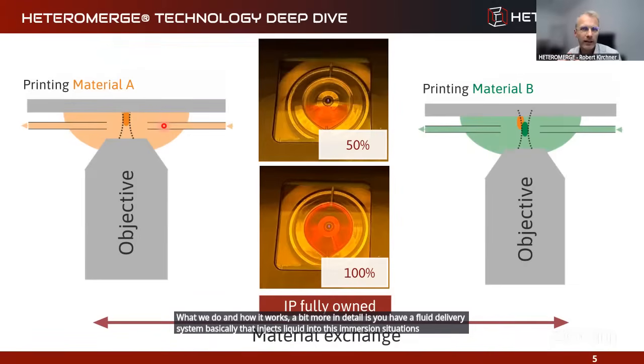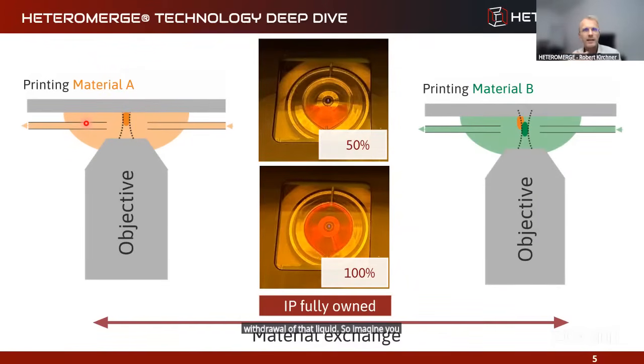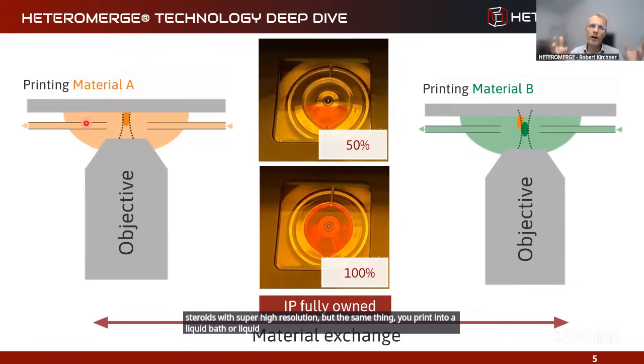So a little bit like in immersion lithography, like a shower head, if you think about this, but not as complicated. But basically you inject liquid and that will blow up your printing volume, and you don't want that. You have a synchronized withdrawal of that liquid. So imagine you print like an SLA 3D printer on steroids, so super high resolution, but the same thing: you print into a liquid bath, and you just swap out this liquid bath in a very fast way. So that's what you see in a nutshell here.